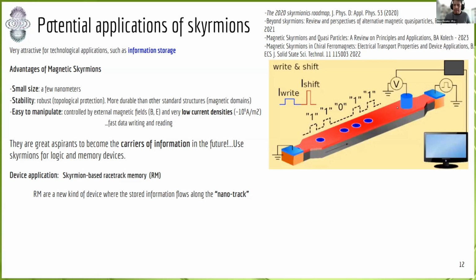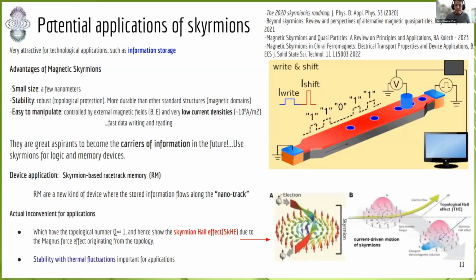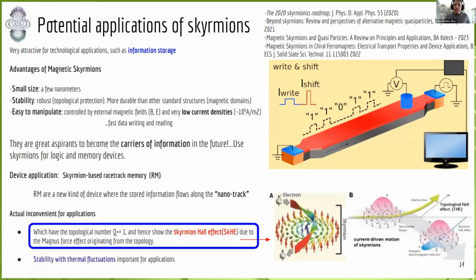This is a very nice idea, very nice animation, but you know that there are always many inconveniences in using physics in applications. Here, I want to highlight only two, which are related with my recent research. The first one is the skyrmion Hall effect. Maybe you know the Hall effect, the standard Hall effect of electrons in a magnetic field. Here is the same idea. The problem is that there is an effective magnetic field induced by the topology of the texture. And then when skyrmions move along the track, they present a perpendicular deflection to the motion. And then it's not good to create these kinds of devices.